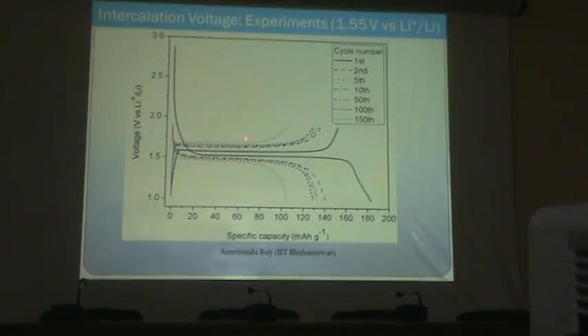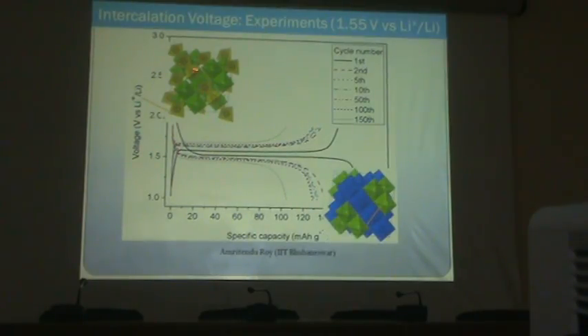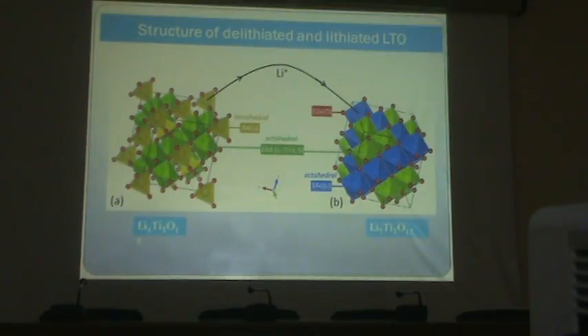More or less you can see the intercalation voltage around 1.55 or 1.6. What happens is your spinel structure changes to a rock salt structure. He took this data and this structure, and calculated the structure parameters and everything. I am not an expert in it, so if you ask me too much, I will raise my hands up.